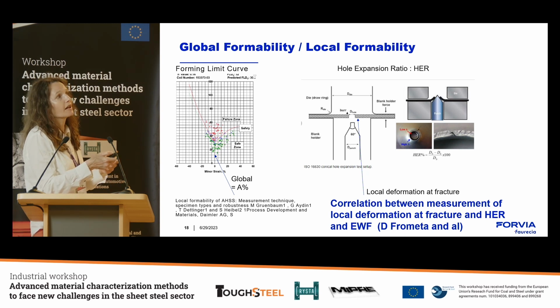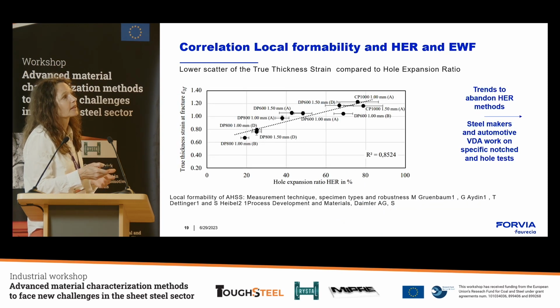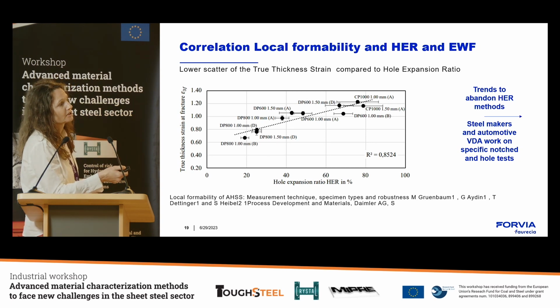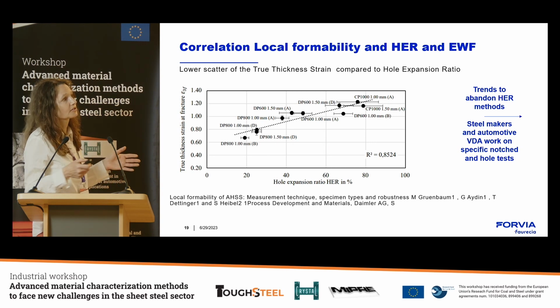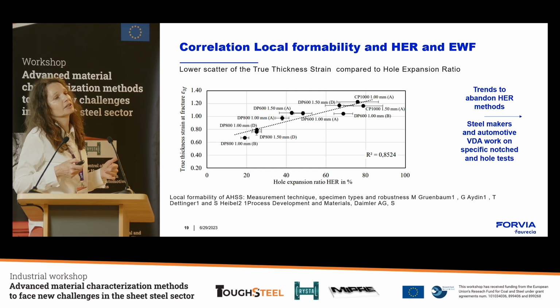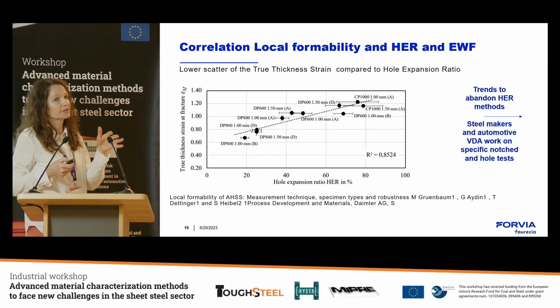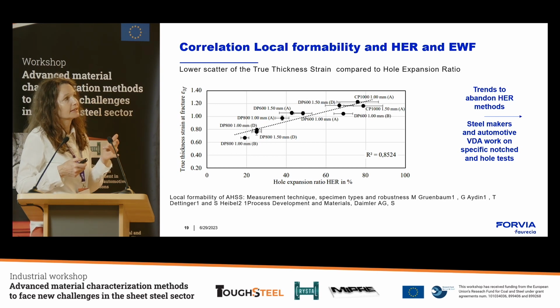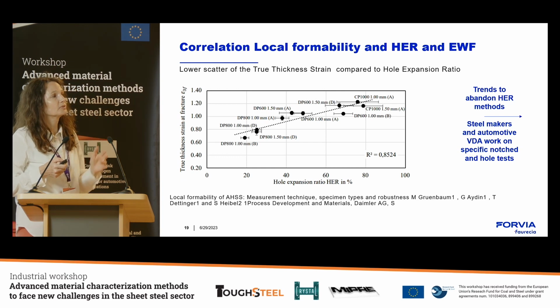So even if David and also Frómeta show that there is a good correlation between hole expansion ratio and the essential work of fracture, I think there is something more, because this is a graph also coming from Daimler that shows the large scattering of the hole expansion ratio. And also, even in Germany, we have different contacts with the material suppliers. There is a trend to drop this methodology because it's not consistent enough for the advanced strength steel, where we are looking for accurate results.